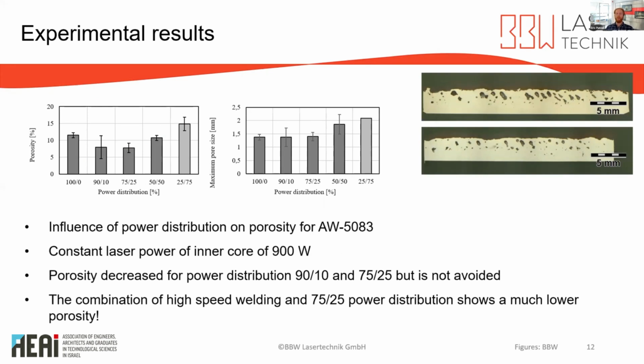So the porosity is at 12% for the power distribution of 100% into the core fiber. And it decreases for power distributions 90 to 10 and 75 to 25% to a porosity of around 8%. So with increasing power feeding into the outer ring, the porosity increases again. And the highest porosity is measured with a power distribution of 25 to 75. So it is very possible that a minimum optimal parameter set exists between 90 to 10 and 75 to 25%.